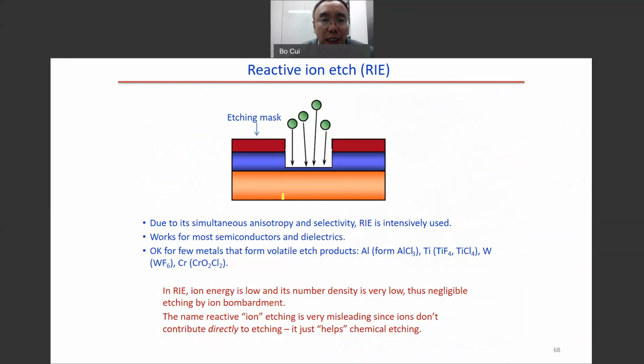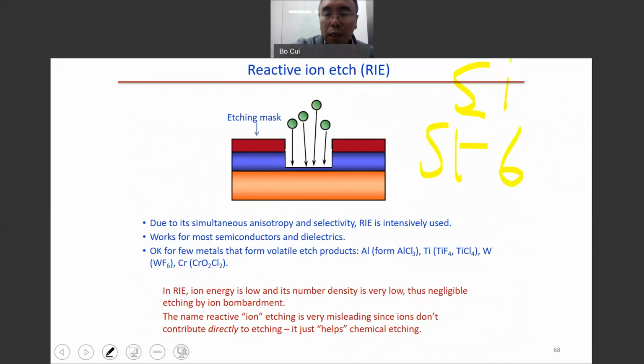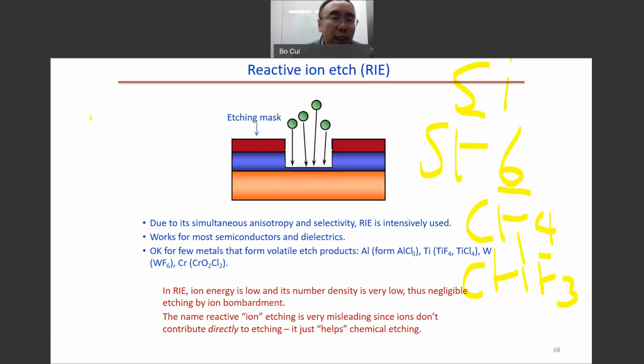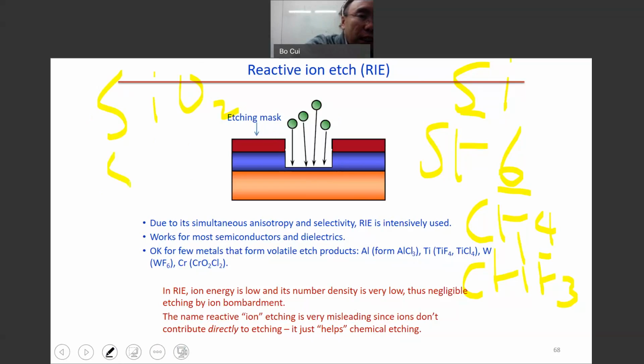Because the RIE can achieve both anisotropy and selectivity as well as high etching rate, it is very heavily used. It works for most semiconductors and dielectrics. Previously we have seen the etching of silicon. For the silicon etching, we can use SF6 gas, or CF4 gas, or CHF3 gas. So we can use those gases to etch silicon. We can use similar gases to etch silicon dioxide. So silicon oxide can also be etched by those gases. The same thing is true for silicon nitride. They can all be etched easily.